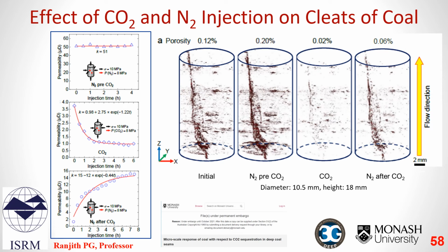As I discussed earlier, one of the main technical barriers for CO2 sequestration in coal is that CO2 absorption induced swelling reduces coal permeability and hence CO2 injectivity. Some field and lab experiments demonstrated that injecting pure nitrogen over a period can reverse some of the reduced permeability.